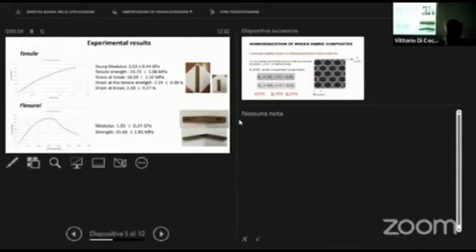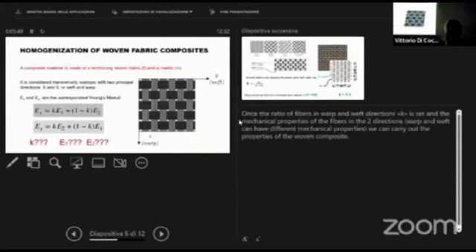the fibers have a higher elastic modulus, and the final product does not approach this value. This is due to the fact that the fibers don't work at their best. As I said before, we determined the elastic modulus using a simple theoretical approach.